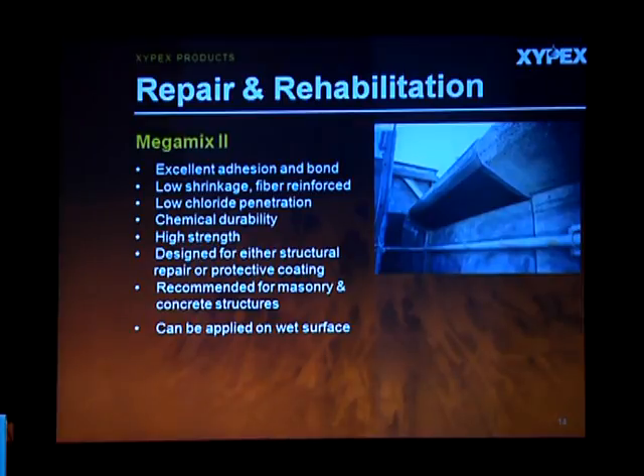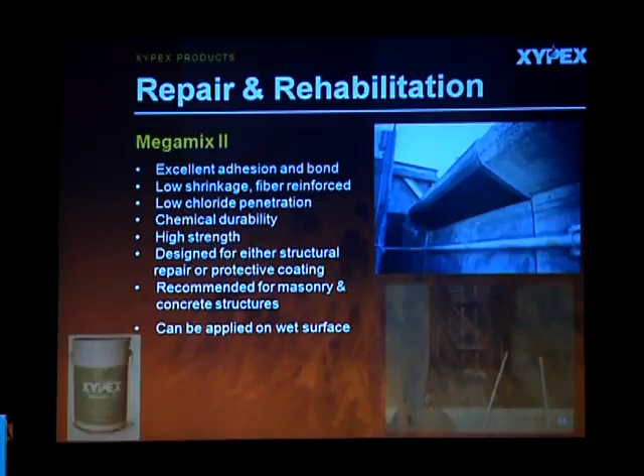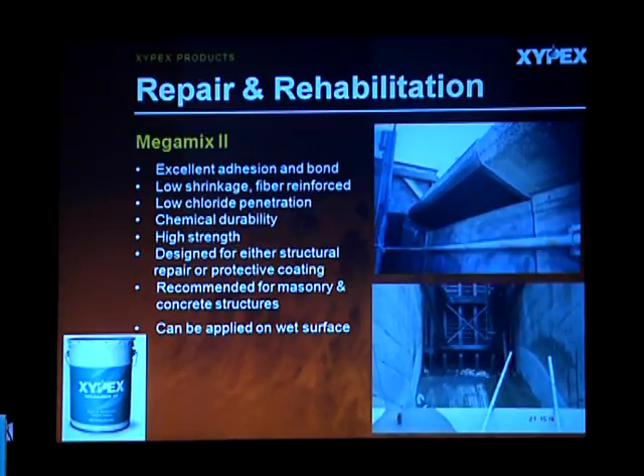And then we have a number of situations where we have a loss of surface or abrasion on the surface because of several factors, especially in the spillway basins or the piers of the spillways. We have this high strength repair material which can restore those lost surfaces, and the strength of this 12.5 mm thickness material is almost M60 grade in 28 days' time.